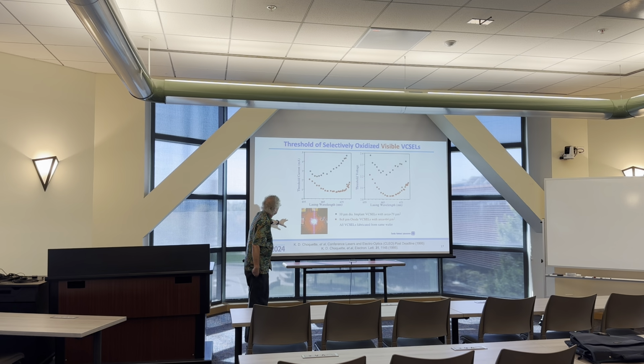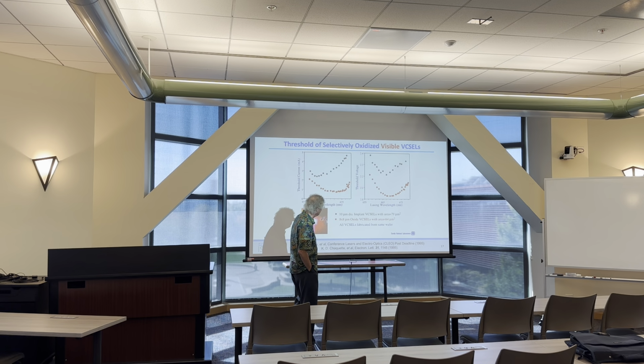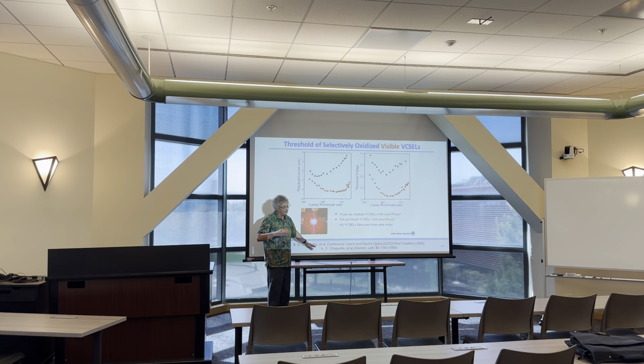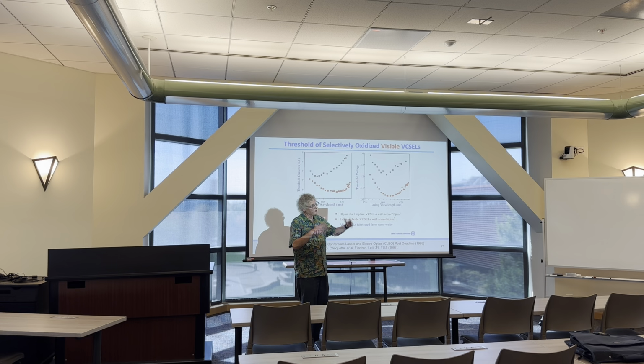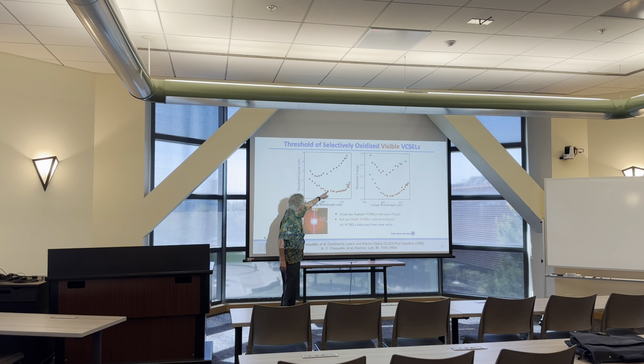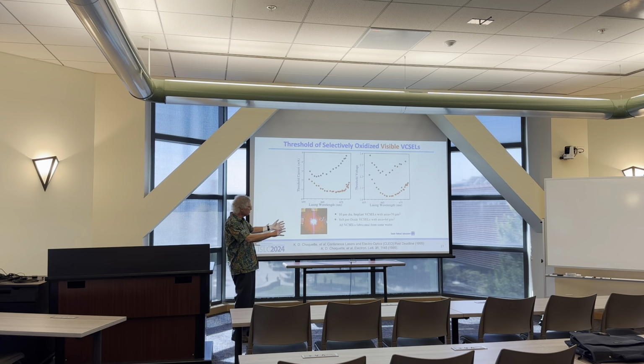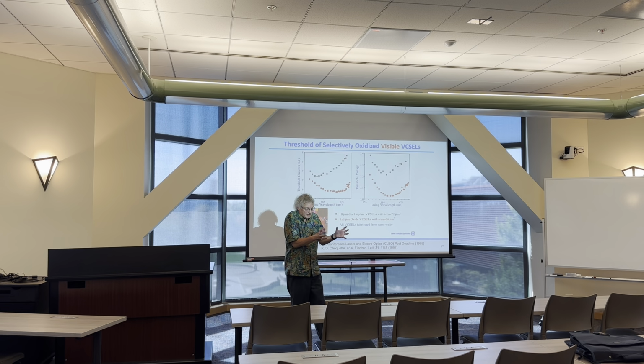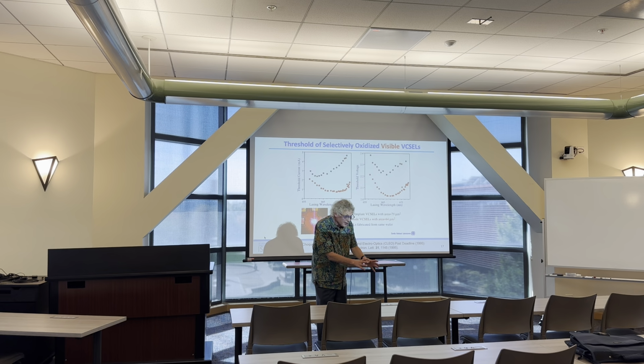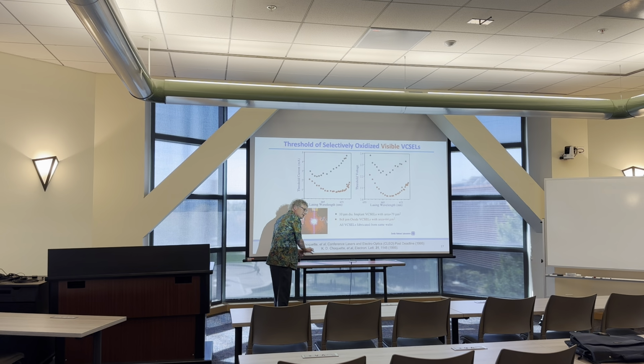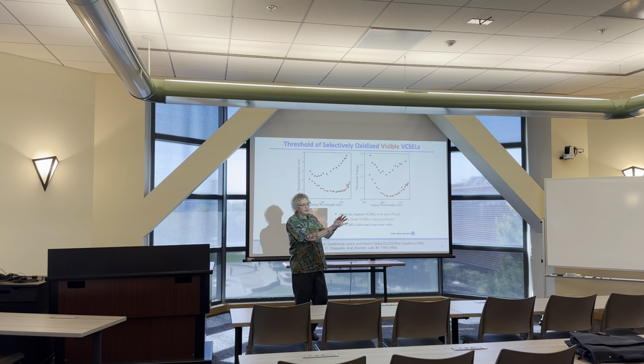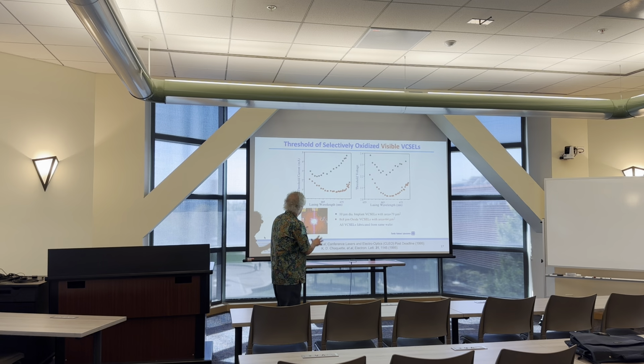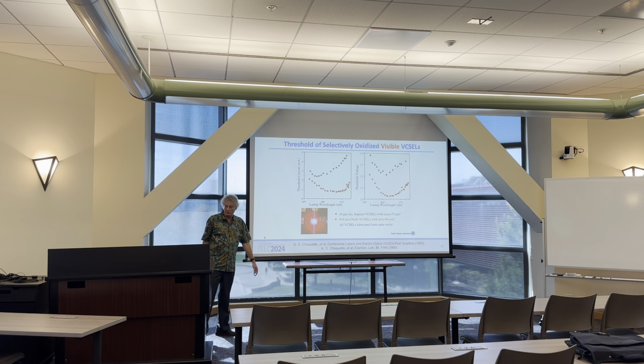Anyway, we also looked at visible VCSELs, and actually at the time, that's what I was hired to do, was to work on the visible VCSELs. So the first thing that Rick did was he put these oxide apertures in there, and overnight, again, we saw big changes. Getting threshold currents in a visible VCSEL below the threshold was just unprecedented, and this led to a bunch of programs, which led to the formation of what then was called Honeywell VCSELs, which then went down to Texas and became AOC, which then became Finisar, which then became II-VI, which today is Coherent. So this work actually had a big impact in the ecosystem, if you will, of VCSELs.